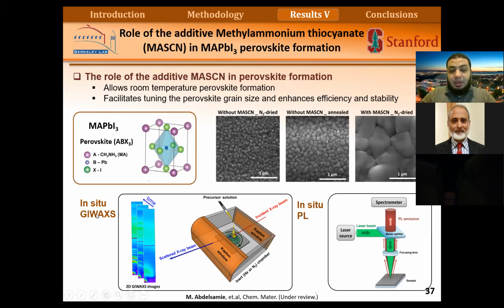And we tried to employ in situ characterization techniques. We applied in situ X-ray, and also we applied in situ PL. The reason for using in situ PL is that photoluminescence is more sensitive to very small nanocrystals, but X-ray needs slightly larger crystals in order to see some diffraction. So the PL can detect the nanocrystals as they form, so it can detect the nucleation and growth.